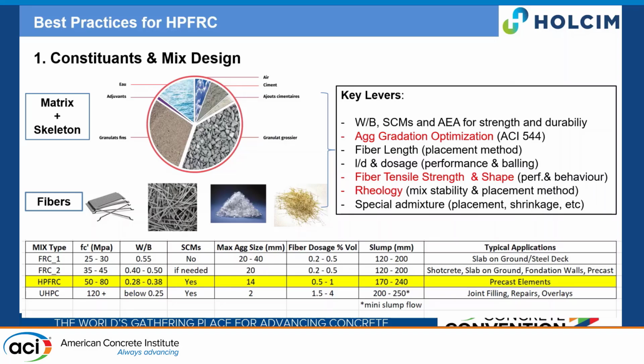to increase the durability? One key aspect, especially when we use high dosage of fibers, is we need to work on the aggregate gradation to make sure that it's properly integrated, especially if you have to pump the mix. And as I said, as you get stronger and stronger matrix, you need to be careful and mindful of the fiber tensile strength and shape, because you can end up with what we call embrittlement. Typically, your fibers can snap.